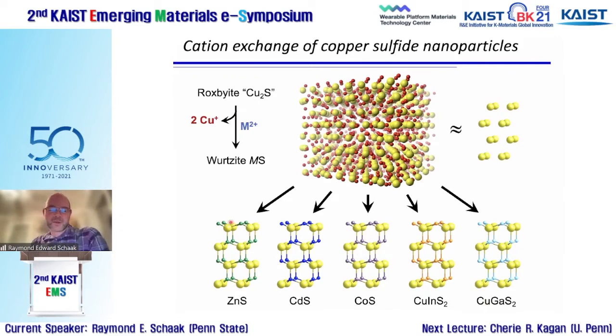But one of the things that you can probably notice right away is that this anion sublattice, this ABAB stacking of the close-packed planes, that stays constant. So for the most part, not always, but for the most part, when you do these cation exchange reactions, you preserve crystal structure. Not only do you preserve the nanoscale aspects, the size and shape and uniformity, but you also preserve the internal atomic level aspects of it, which is the crystal structure.